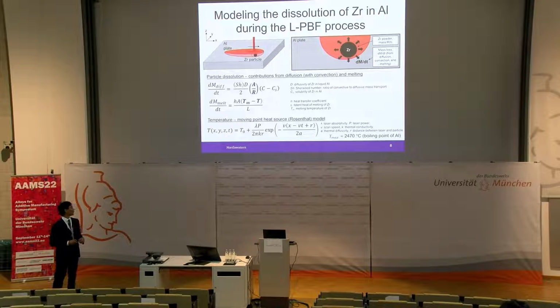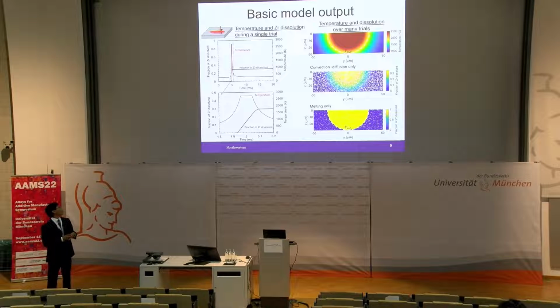The temperature we give by assuming that the laser is a moving point heat source, for which you can use the Rosenthal solution, which we then modify by imposing a maximum temperature to avoid any issues with the singularity when the laser gets very, very close to the particle. When we put all these equations together, we fix the location of the zirconium particle, we allow the laser to move towards it and away from it, and then we measure the temperature during this process, and then we calculate the fraction of zirconium dissolved as a result.